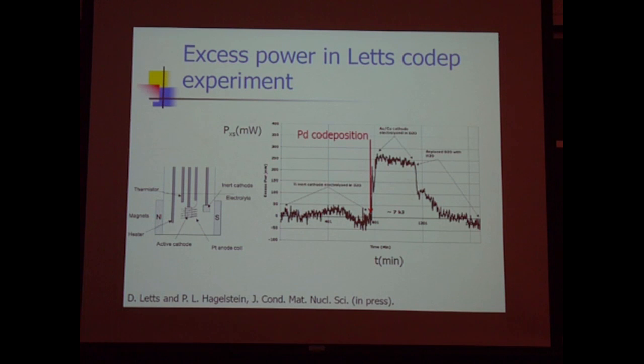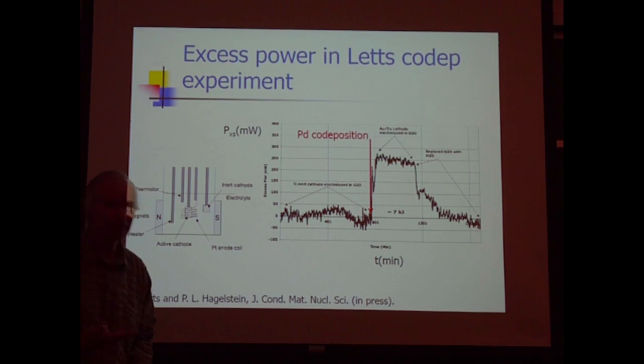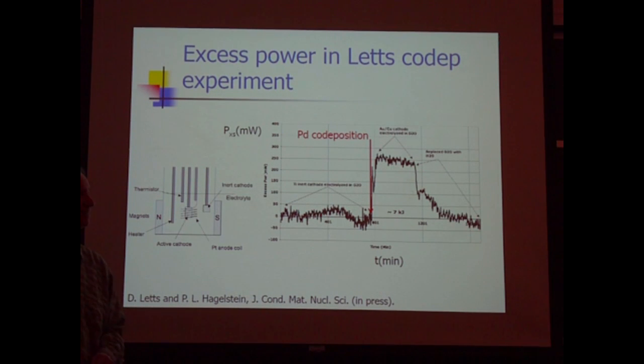So Letts tried Pam Boss's protocol for co-deposition, looked for excess heat, didn't see anything. Dead as a doornail, goose egg. So then Letts was familiar with some of my arguments and my ideas, so I said, well, obviously what's wrong is you've not got high enough loading at the surface when your current density is low. So he said, let's crank up the current density. So he boosted the current density well over 100 milliamps per square centimeter, started co-depositing. The palladium came out, co-deposited like mad, didn't stick very well, fell to the bottom of his test tube. He scratched his head and said, that's no good.